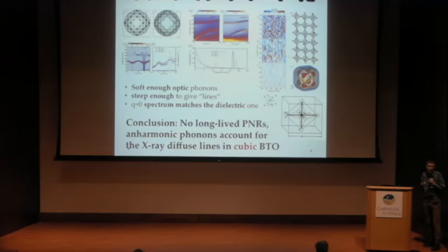So we are basically computing the X-ray inelastic scattering. And we can see that the intensity which is here is coming from the phonons, and especially the comet lines are coming from the overdamped modes, which have this kind of frequency dependence, and the frequency dependence matches the dielectric spectrum, which we know gives the contribution to permittivity. So there is nothing static. It's something which has a time constant of typically a picosecond.